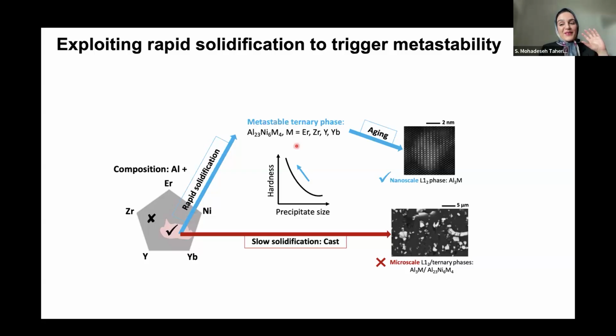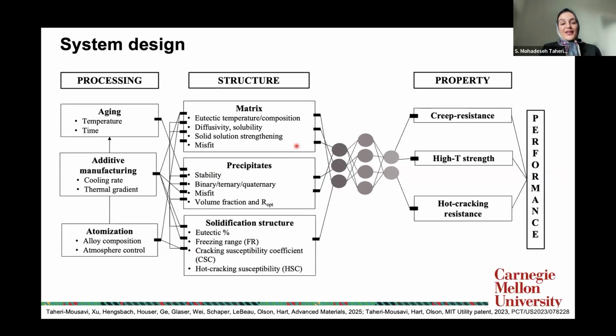This is our main idea, and we finally made this work, but designing an alloy is a complex task. For example, if I wanted to come up with any new recipe, meaning which element should be at what concentration, you should think of this alloy going through powder processing, printing processing, and post-heat treatment processing, each of which has its own parameters. By fixing the processing parameters, you fix what you can see under the microscope of the alloy. And there are many features that you care about that control the properties you are seeking. For us, that was creep resistance, high temperature strength, and we didn't want to see those hot cracks.